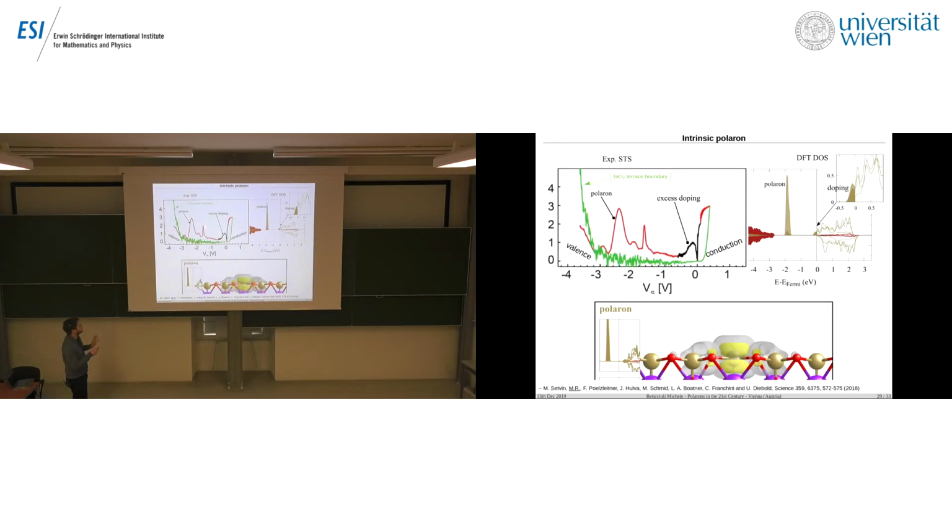Actually, this could be explained too. But essentially, these are polaronic states. And then there is a two-dimensional like occupancy of the bottom of the conduction band. And this is due to the excess doping introduced into the system. In this case it was calcium doping, which brings more electrons into potassium tantalate.